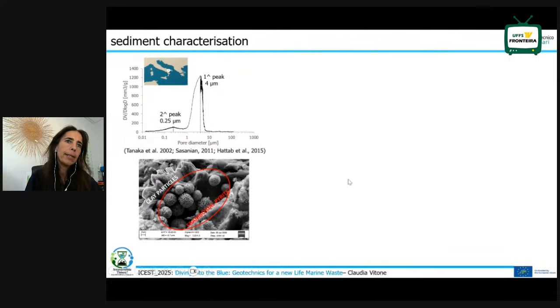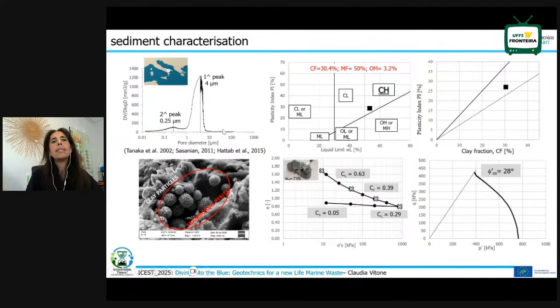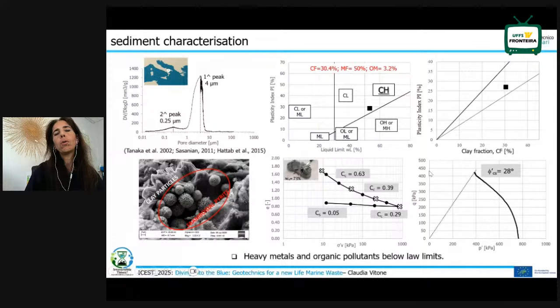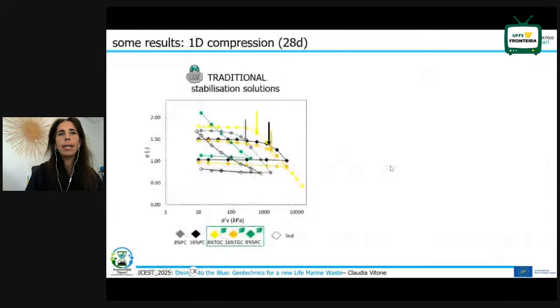Starting from the sediment, it was taken at the beginning from just one site, the site of Taranto. This is a typical representation of marine sediment with a bimodal pore size distribution, a high activity soil. Essentially, this is a clay silt with medium activity, quite high plasticity, a normally consolidated soil, with quite a good friction angle, to be honest. In this case, the sediment was not polluted, neither by heavy metals nor organic materials.